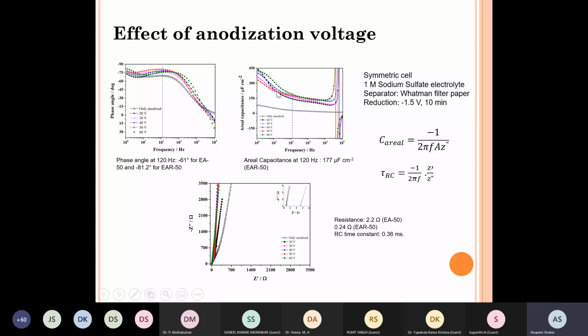And so if you see that there is high capacitance as the frequency is low, so between 1 and 5, you can see high capacitance. It reduces as the frequency goes up, but there is sufficient capacitive behavior still, which is seen with phase angle more than -75. And of course, it continues to decrease as the frequency is increased.